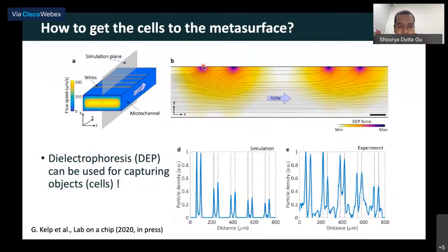Now, these are where the electrodes have been placed, and around the electrodes is where you have the metasurface. So if I have a cell which comes and sticks here, it will be sitting on the electrode and on the metasurface, which is what we'll use. So this is a typical simulation that we get. There are multiple electrodes on the same device, and at each of these electrode interfaces, we'll have a high particle density. So the particles will come and stick onto where the electrodes are, right?